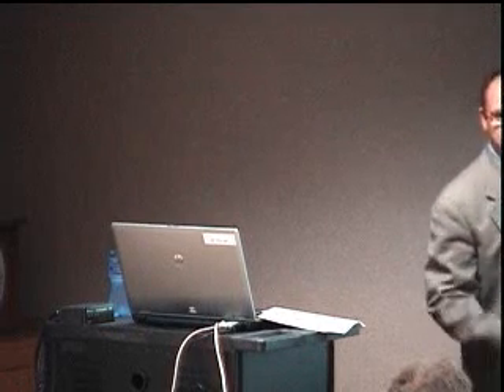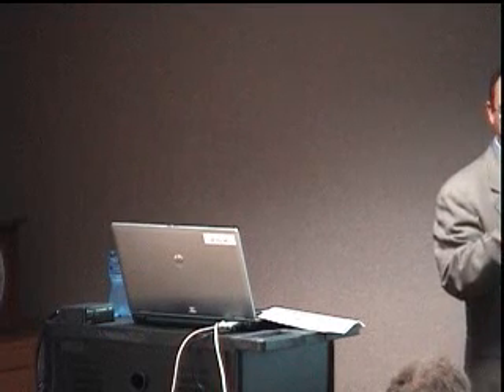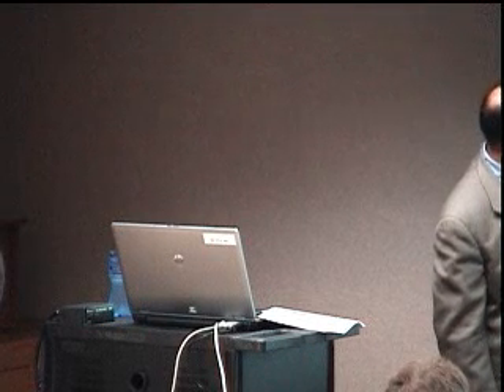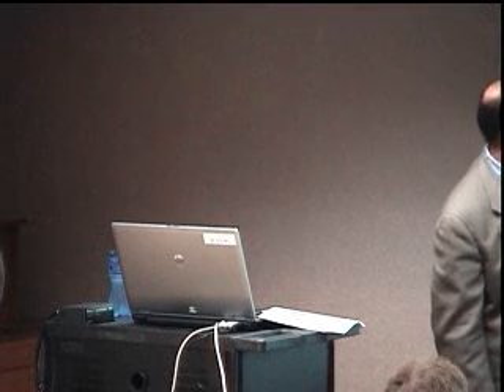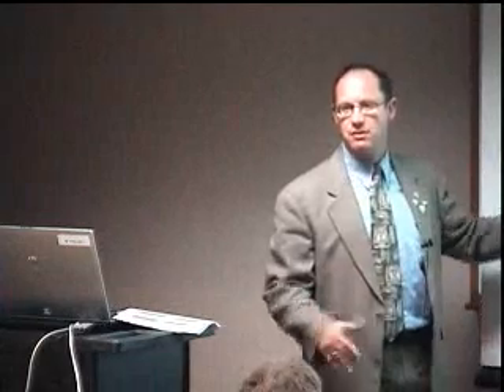To give you an idea, this is about 3 inches. And this is a distance from the surface of the concrete to the bar. This is 2 inches. This is 4 inches. So that's an inch, that's an inch, that's an inch. You can see that the depth is generally about 3 inches, really plus or minus no more than about a half inch. So by and large, those bars are where you would expect them to be.